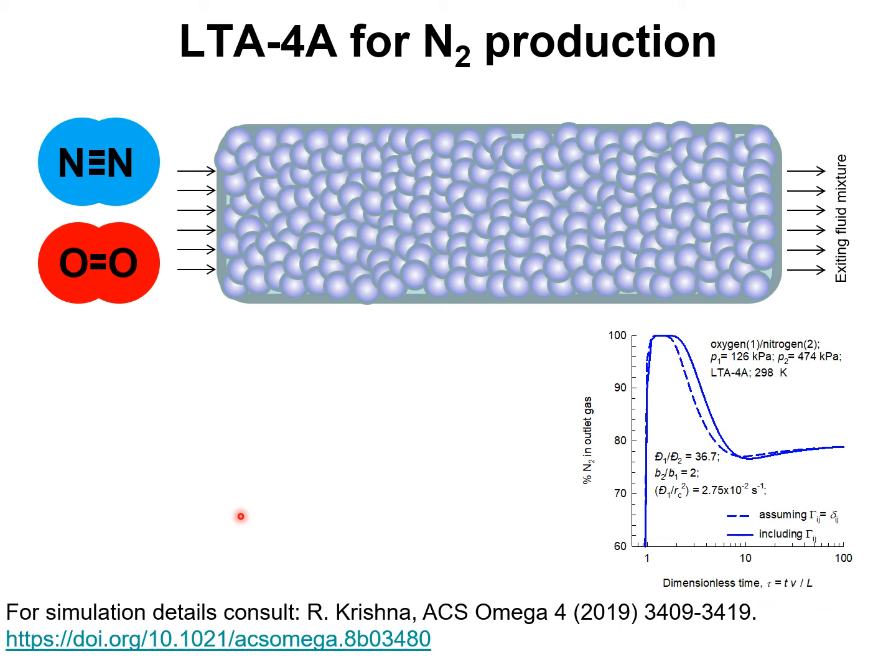To demonstrate the importance of thermodynamic coupling in kinetic separations of oxygen-nitrogen mixtures in LTA zeolite, we perform transient breakthrough simulations for 21:79 oxygen-nitrogen mixtures at a total pressure of 6 bars and temperature of 298 Kelvin. The simulation details are available in my 2019 paper.